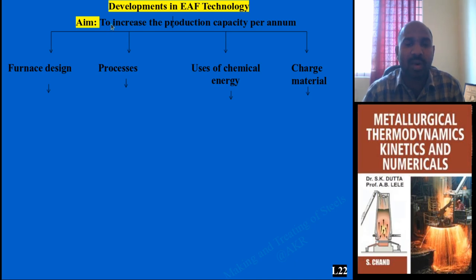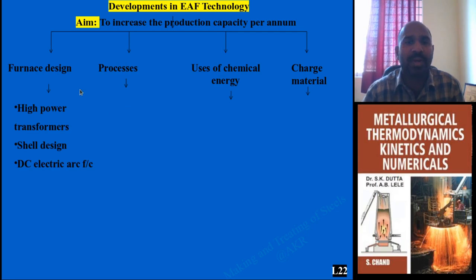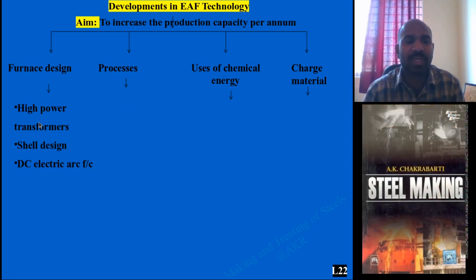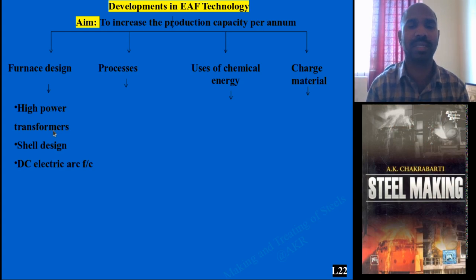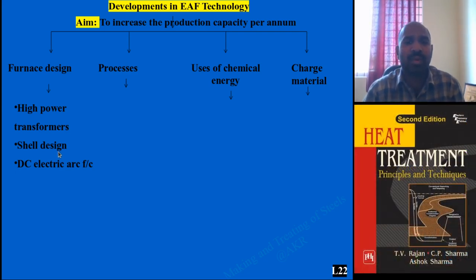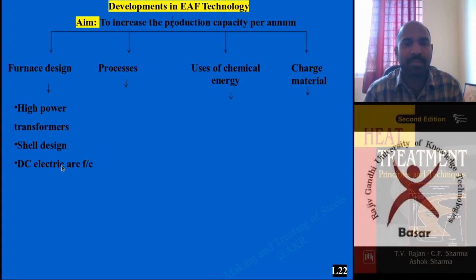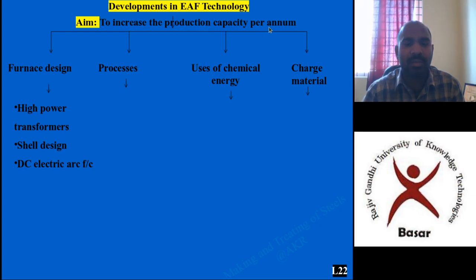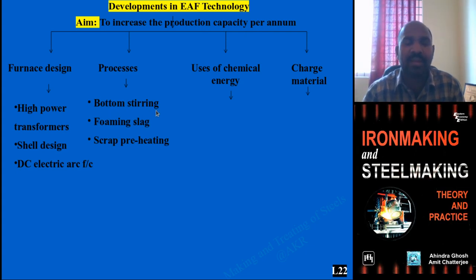This is how the developments are designed step by step. Coming to furnace design, instead of a low power transformer, if you use a high power transformer, you can get higher capacity. Shell design — with respect to shell thickness and shell dimensions — if you change these, it will affect the capacity. And instead of using an AC electrical furnace, if you use DC, you will get better quality of steel. Coming to the process, if you adapt a bottom stirring process with inert gases, you can get a homogenized composition.